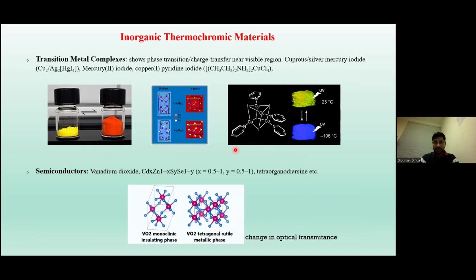Apart from these transition metal complexes, we also have the semiconductor vanadium dioxide, which is very frequently used for developing thermochromic systems. They basically change from monoclinic to the rutile phase when we apply heat, and because of their changing from insulating to metallic phase, there will be a change in their optical transmittance, resulting in their thermochromic behavior. So this type of materials can be useful for this purpose.